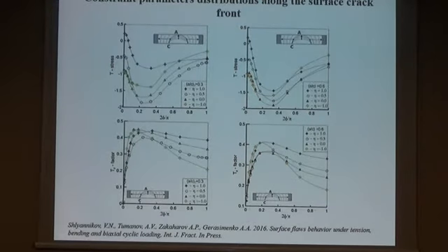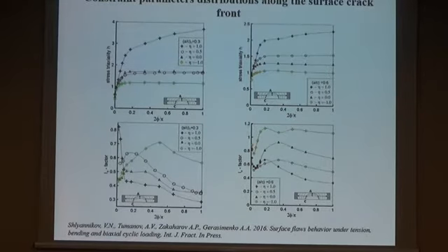In this figure, you can see the distributions of in-plane T-stress parameter and out-of-plane TZ factor along the crack front of surface cracks. These distributions of constraint parameters are presented for the two positions of surface cracks with aspect ratio 0.3 and aspect ratio 0.6. In this figure, you can see distributions of stress triaxiality parameter and governing parameter of elastic plastic stress fields, Q factor. It should be noted that all of these constraint parameters significantly change along the crack front, and they are also functions of loading biaxiality.